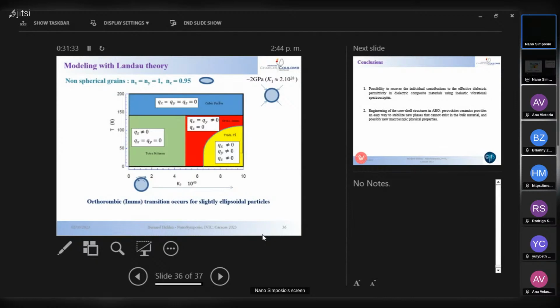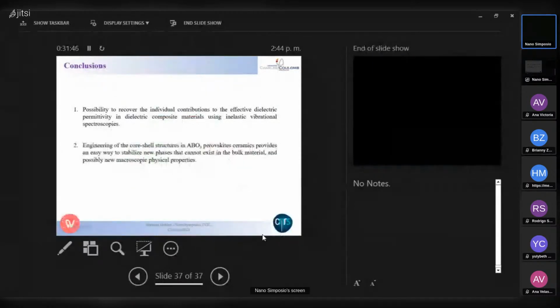So this is to say that you can completely change the property of a grain depending on the stress you put on it, on the shape of the grain. So I come to my conclusion. In the first part, I've shown you that it's possible to reconstruct the effective permittivity of a sample using inelastic vibrational spectroscopy. And here, I show you that by inducing uniaxial pressure or shear stress on samples, you can induce phase transitions which are not expected in the bulk materials and which can be helpful for new physical properties eventually. Thank you for your attention.